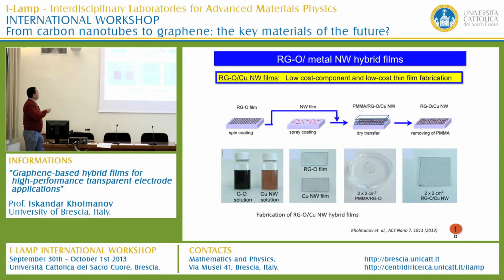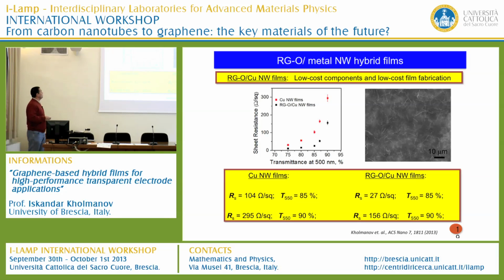So what we did, we simply used copper nanowire. This is also in solution, and we used the graphene oxide solution. We deposited these two different films on two different substrates. Then in the next step, we reduced the graphene oxide and obtained the reduced graphene oxide film. We delaminated the reduced graphene oxide and put it again on top of the copper nanowire film. In this way, we obtained a reduced graphene oxide copper nanowire film. The fabrication has some tricky details, which you can find in our recent publications.